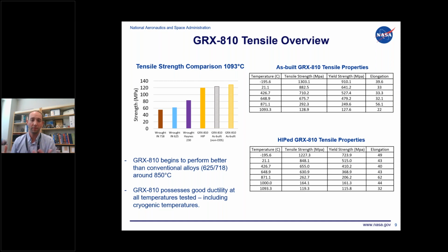But when we explore this alloy compared to more conventional 718, 625, and even Haynes 230, what we find is that by the time you get to 2000 degrees Fahrenheit, you start to really see the benefit that these oxides have on the tensile properties. You can see on that bar chart on the upper left, almost a 2x improvement in tensile strength with GRX-810 versus your wrought 718 and 625 alloys.